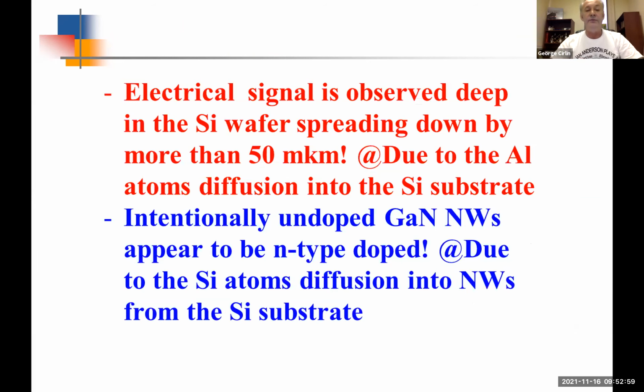So this is the conclusion of the first part, and what we found here is that electrical signal was observed deep in the silicon wafer, to a depth of up to 50 micrometers, and this is due to the effective aluminum diffusion of atoms into the silicon substrate. Additionally, intentionally undoped gallium nitride nanowires appear to be N-type doped, and we believe it's due to the efficient silicon diffusion from the substrate into the gallium nitride nanowires.